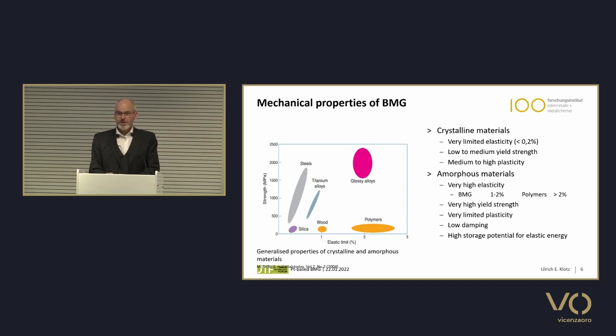We see some non-metallic materials like silica, wood, or polymers. They have much lower strength, but polymers have really high elastic limits of about 2 to even nearly 3%. So this is, we know it, and rubber is even more. We know that the material is soft and can be bent forth and back without being deformed. And bulk metallic glasses show also very high elastic limit, quite comparable to polymer materials. So this is really unique for metallic materials, and this is therefore quite interesting, these very different properties. How can we use it?